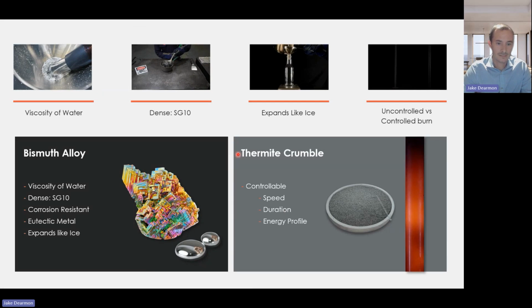Couple that low viscosity with a high density, and it's a really good pair. Bismuth alloys are very dense. They have a specific gravity anywhere from 9.5 to 10.5, so they're very, very heavy. This high specific gravity actually allows the bismuth alloys, coupled with that low viscosity, to displace wellbore fluids. So any solids or anything that might be around that plug when it's a liquid actually float to the top.